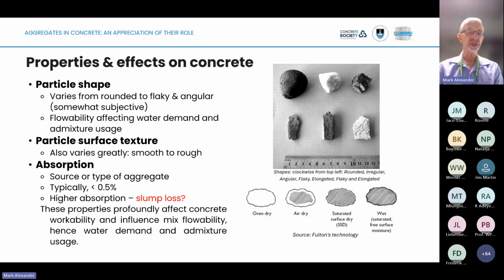Right, moving on. Particle shape is an important aspect, along with surface texture and absorption. These three are really quite critical because they have very profound effects on water demand or water requirement for concrete. If you can see the figure up on the right, moving from the top left and going clockwise, you're going from, let's say, the best particle shape, nicely rounded, right to the one on the bottom left, which is angular and flaky. We don't particularly like that kind of shape in our aggregate because it usually causes a lot of internal friction and lockup. And then we have problems with workability. We like the chunky aggregate shapes, which are at the top right or maybe the bottom right at the most. Those give us reasonably good concrete properties.